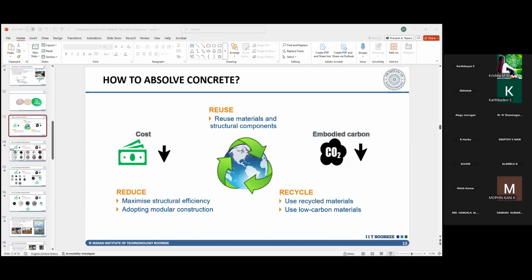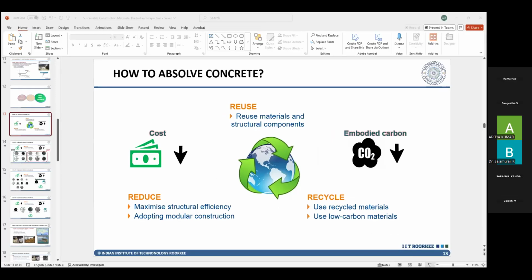So what we did in Singapore was we used clay, which if you heat, you will be able to produce a pozzolanic material that can be used as an alternate to cement. And not just that, if you use it in the right amount, it can not only impart good strength, it can also improve your durability. And in India, you have IS codes for Portland calcined clay pozzolana, as well as a very recent code, I forgot to mention here, IS 18189, which came a couple of years back. That's on limestone calcined clay cement, LC3.